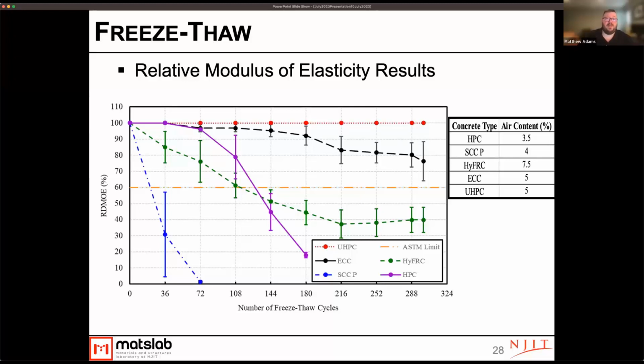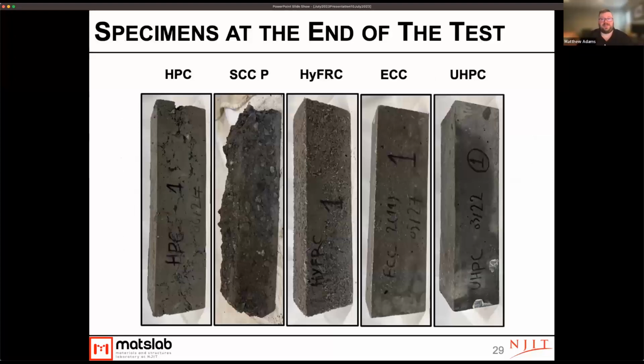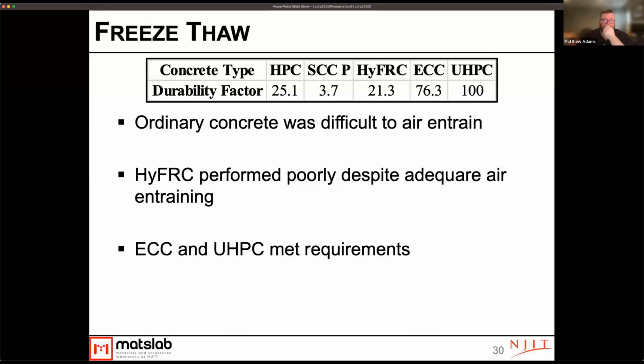performed really well. And so we can see these are what the specimens looked like at the end of testing. The UHPC and the ECC basically look completely undamaged. And so they performed really, really quite well in freeze-thaw testing. So what we know is that our ordinary concrete was difficult to air entrain. Likely these results show that if you don't get enough air entrainment in there, you're definitely not going to get good freeze-thaw performance. Even though the HyFRC did perform poorly, we need to take a look at that a little bit more, but some encouraging results with the ECC and UHPC.